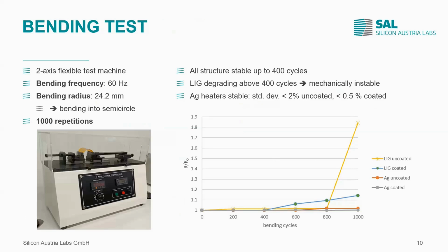Good. Last but not least, we are always talking here of flexible heaters, so we also want to show that they are really flexible. We went for bending tests and put them in a 2-axis flexible bending machine. We did 1000 repetitions with a bending radius of 24.2 millimeters, which bends the samples into a semicircle. Up to 400 repetitions, all our samples kept stable. Above that, the silver samples kept stable, but the LIG samples started to degrade, the coated one less than the uncoated one. We checked that under the digital microscope. This happened because the LIG starts to ablate and peel off from the substrate after several bending repetitions, and therefore you lose conductivity.